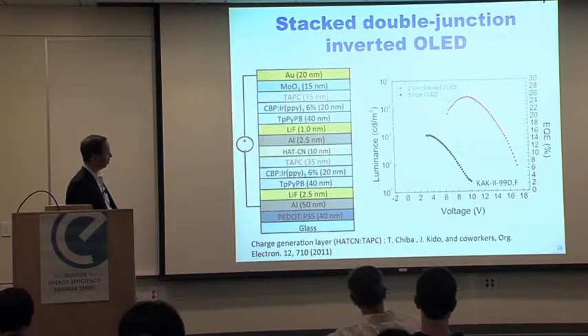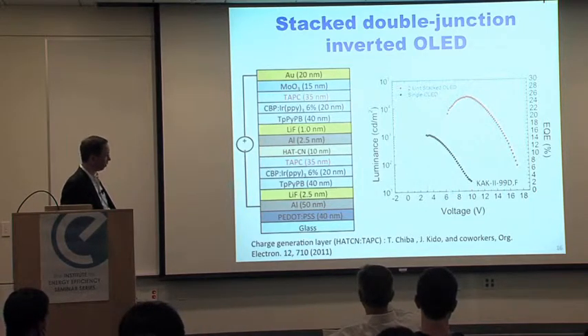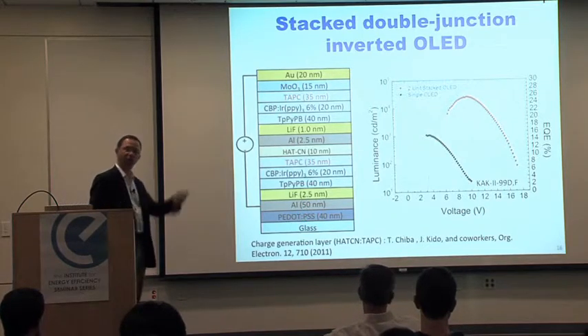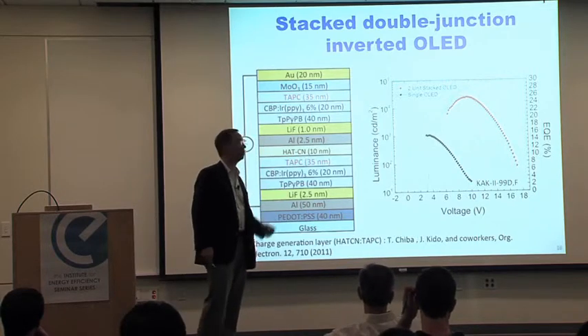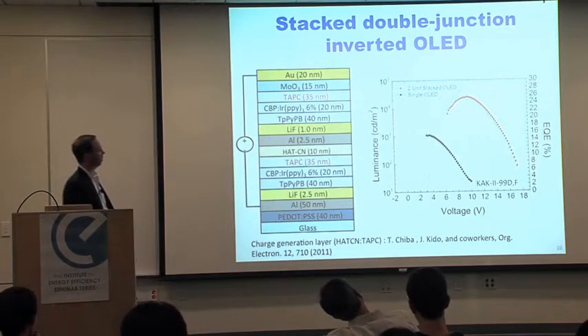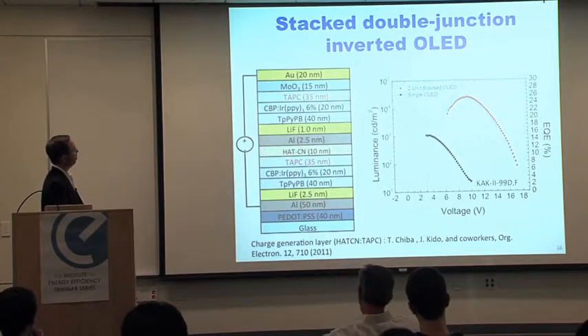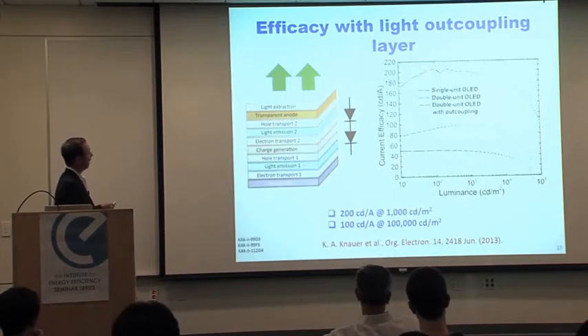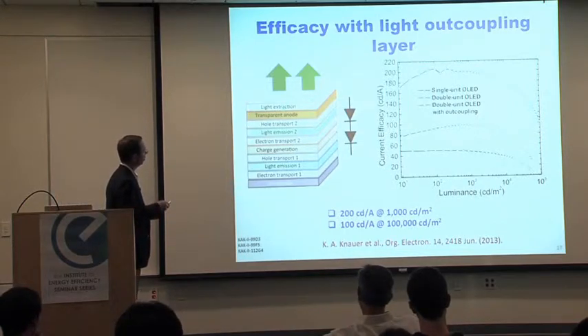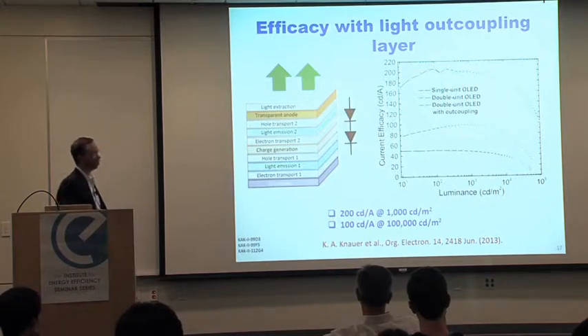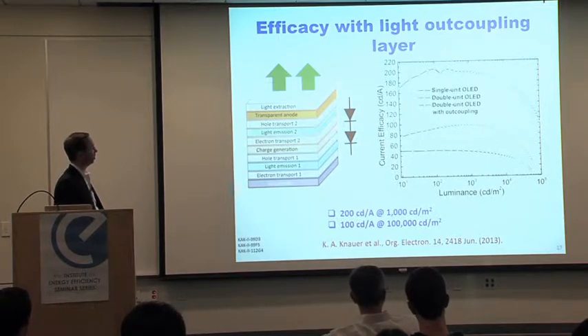You see the curve in black here is the external quantum efficiency, and here the light output of a single layer diode. If you take a double layer diode, you can nearly double the efficiency, because for the same current, the current is now flowing through two junctions, and so you have two junctions that emit, and so you have a higher light output. If you play with that light outcoupling layer here, and you add a thin high index layer on top of that top electrode, you can further increase the performance of your device, and you can significantly increase the amount of light that is coupled out of this device.